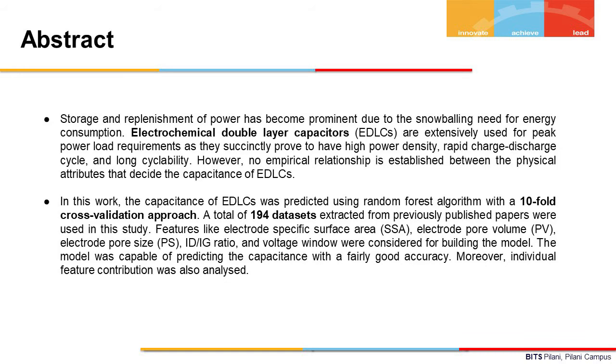In our study, we have tried to estimate the capacitance of EDLCs using a random forest algorithm alongside a 10-fold cross-validation approach. We have used 194 datasets in total, consisting of data points collected from previous literature. The features or attributes of the EDLCs that have been considered are electrode specific surface area, electrode pore volume, electrode pore size, ID/IG ratio, and potential window. I will be explaining this in detail in the following slides, but first, let me speak a bit about batteries and EDLCs.